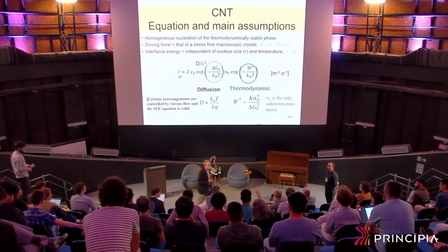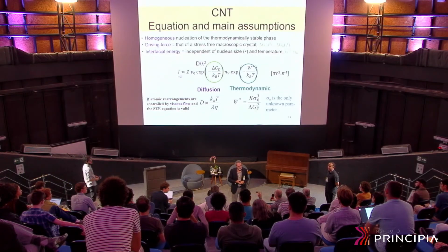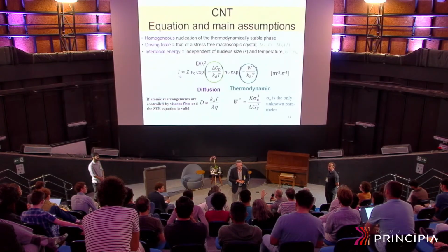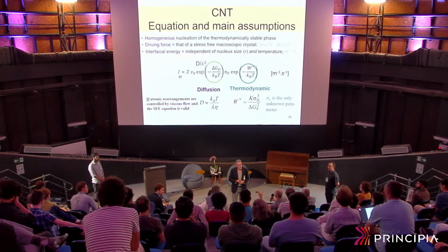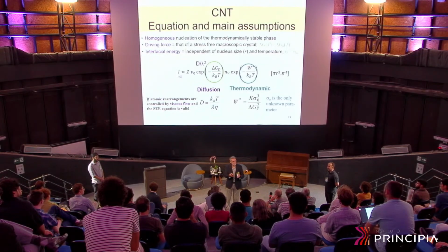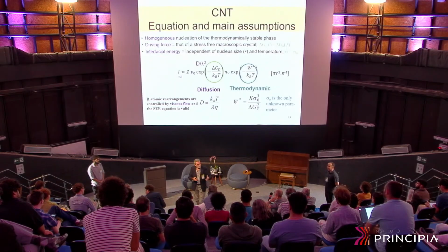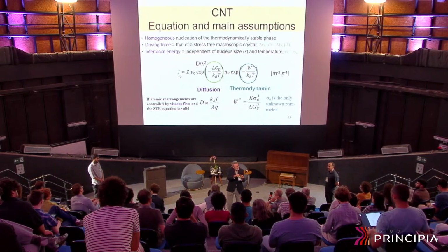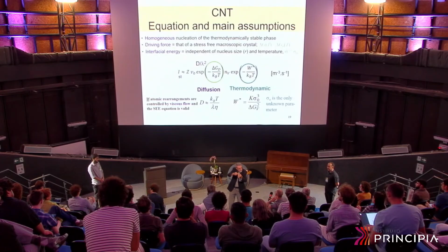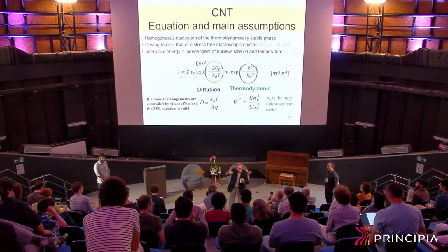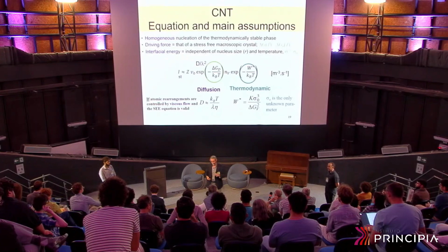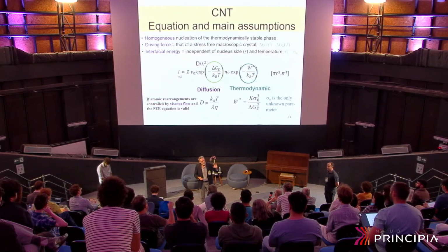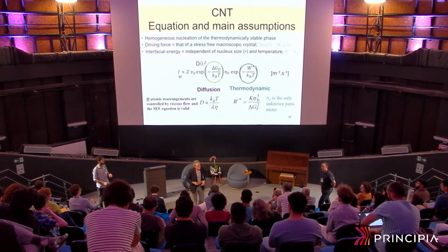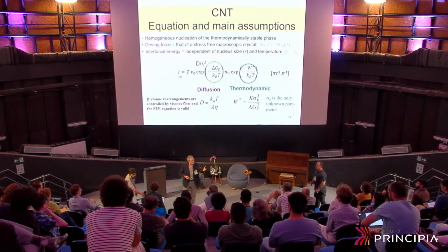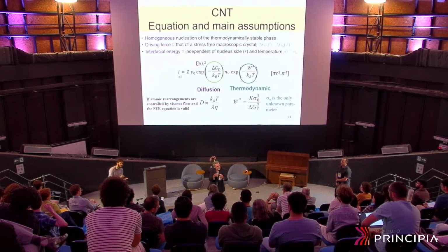Besides the temperature dependence, you also have the curvature dependence of the surface tension. If you have these nanoscopic systems, you should also worry about the curvature dependence. You were right, but they are embedded. There's the Tolman equation, and both dependencies are embedded in the fitted evolution of the interfacial energy with temperature that I showed. But you can do the same kind of calculations just assuming a curvature dependence. Because the nucleus size increases with temperature, they are interrelated.